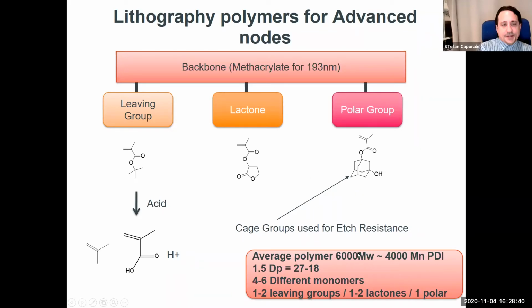Again, these are very small polymers when it comes to the size of things for any of the polymer chemists in the group. We're looking at a molecular weight, a Mw, of about 6,000, Mn of 4,000. So you're looking at about 16 to 18 molecules in that chain on average, versus, again, high density polyethylene that's used to make plastic bags and stuff, which is about 50 to 70,000 molecular weight. So again, these are very small polymers but made of very large monomers, and that gives some very unique properties.